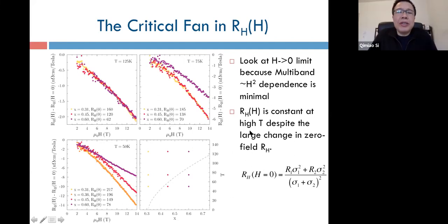Any other questions, comments? Maybe I can ask a question following the lead you were giving towards the end of your talk, connecting different materials. The Hall coefficient in heavy fermion quantum criticality going to vanadium doped chromium, etc. They seem to have very contrasting behavior, and there are various ways of analyzing it. But one way that has been fruitful in those two types of systems for comparison is to look for the isothermal dependence of the Hall coefficient and see whether, first of all, there's any rapid change in the vicinity of the quantum critical point, and if so, whether there's a sharpening as a function of temperature.